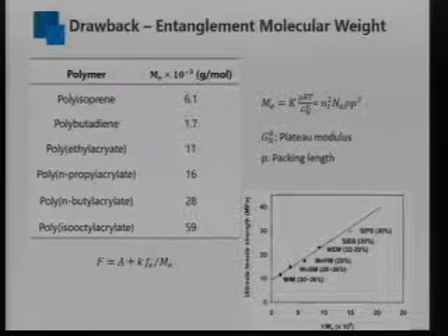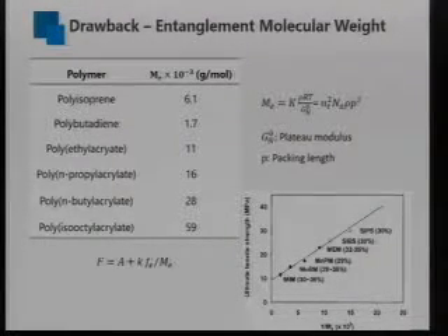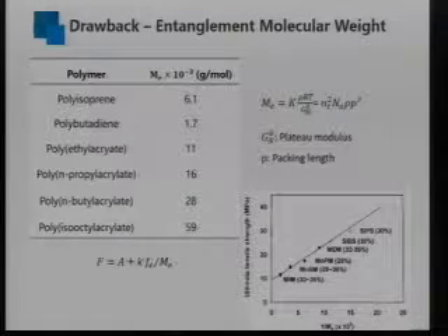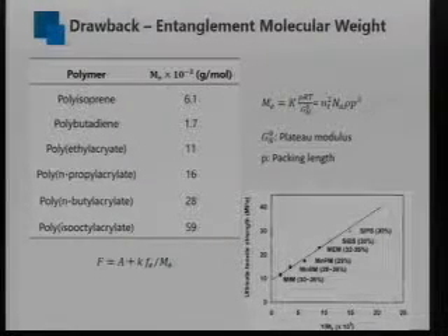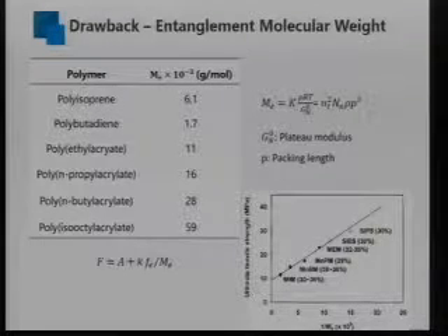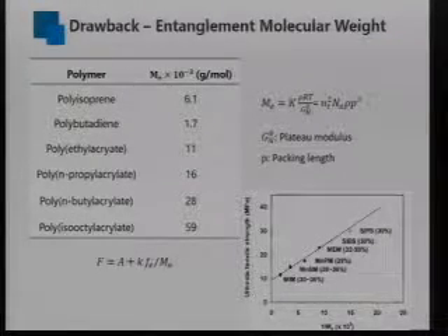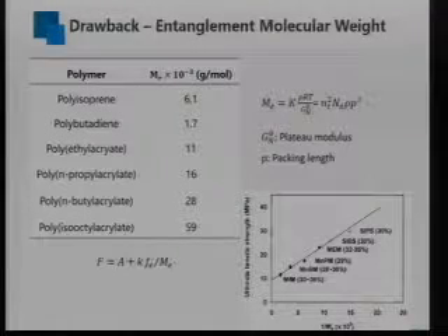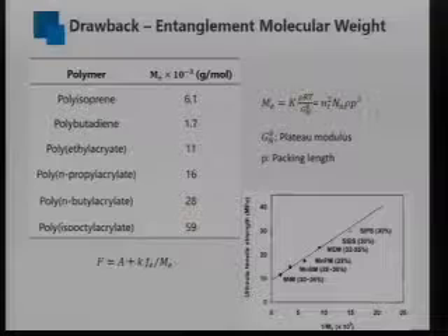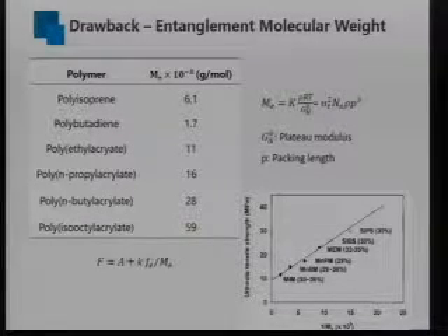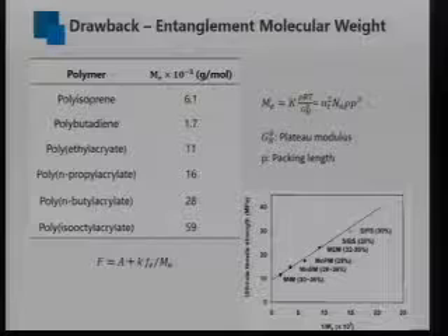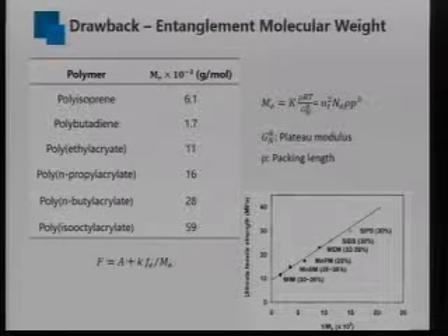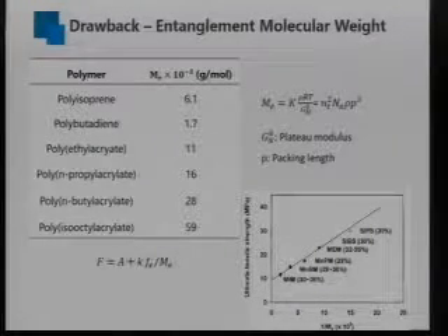However, the mechanical property of acrylate-based thermoplastic elastomers is always disappointing because of the term called the entanglement molecular weight. The entanglement molecular weight of this kind of acrylate-based thermoplastic elastomer is always much higher than the polydienes. The entanglement molecular weight, in definition, means the molecular weight between the temporary entanglement junctions. So with the same molecular weight of the polymers, a higher entanglement molecular weight means you will have less entanglements. In this way, the mechanical property is always much weaker as compared to Styrenic thermoplastic elastomers.